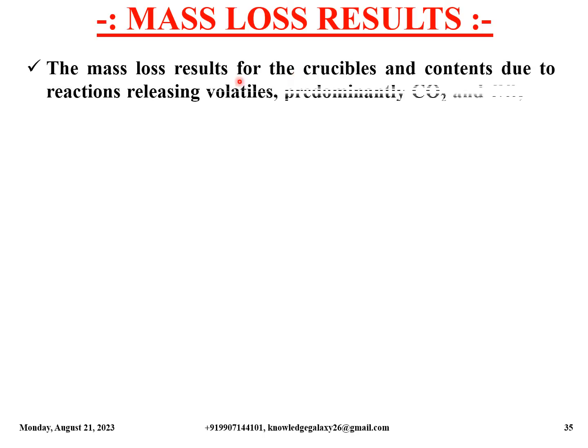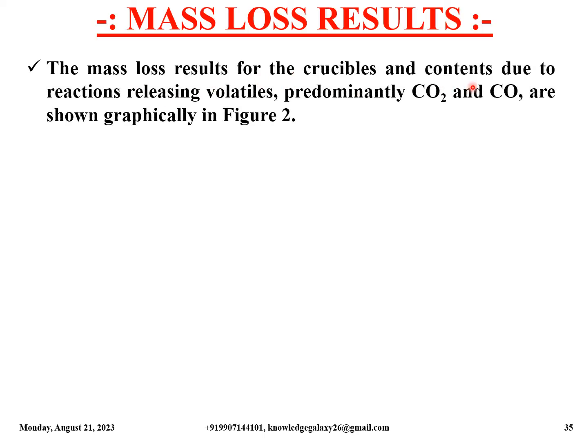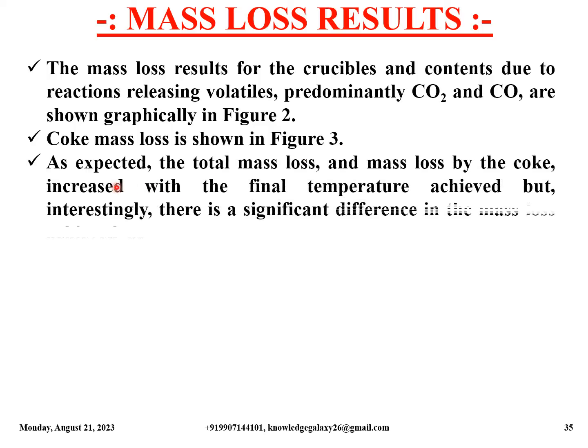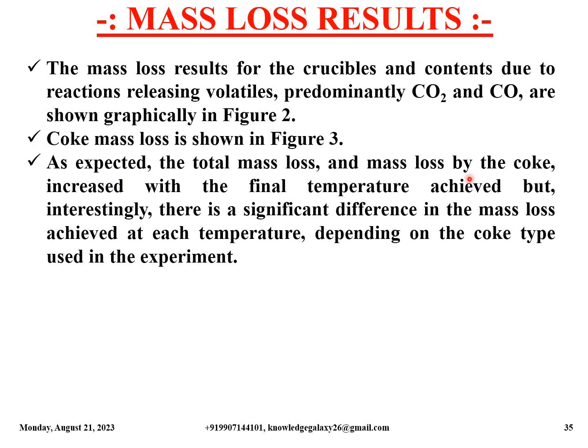So now let us discuss mass loss results. The mass loss results for the crucible and contents due to reactions releasing volatiles, predominantly CO2 and CO, are shown graphically in figure 2 in the coming slides. Coke mass loss is shown in figure 3 in the coming slides. As expected, the total mass loss and mass loss by the coke increased with the final temperature achieved, but interestingly, there is a significant difference in the mass loss achieved at each temperature, depending on the coke type used in the experiment.